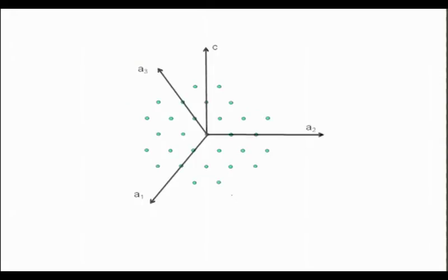So now let's try to draw the direction, okay. So in this case, let's say I want to draw a direction [1 2 0]. This is a hexagonal basal plane, and I am drawing [1 2 0]. [1 2 0] is simple. I go 1 along A1 axis and 2 along A2 axis, and then join with the origin. So that is what I will do. This will be the [1 2 0] vector.